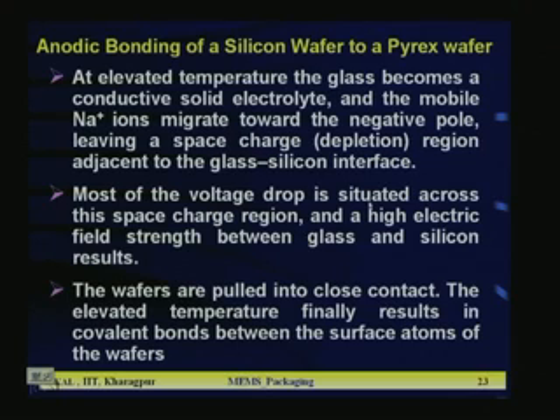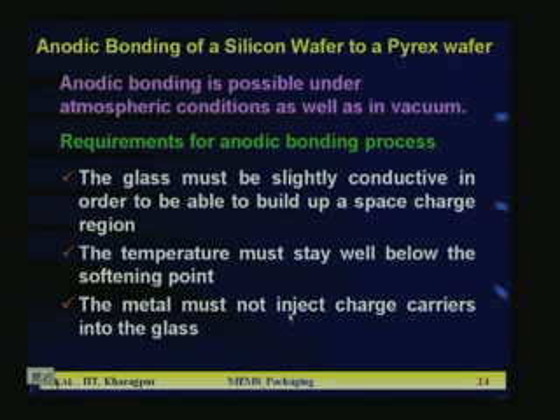Most of the voltage drop is situated across the space charge region, and a high electric field strength between glass and silicon results, because that region is very small. We know in the case of p-n junction devices also, the field is maximum in the depletion layer region. The wafers are pulled into close contact because of that high field. The elevated temperature finally results in covalent bonds between the surface atoms of the wafers.